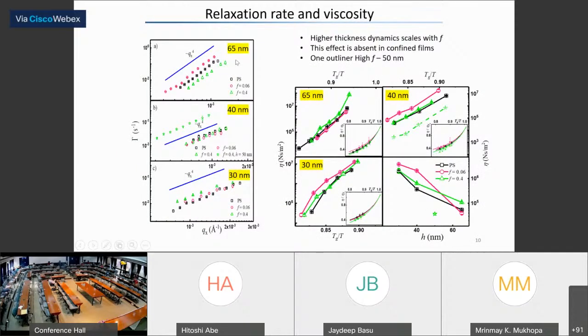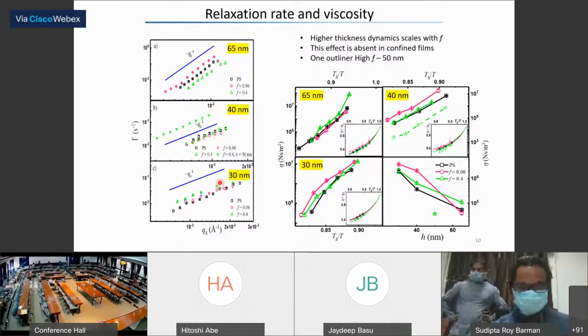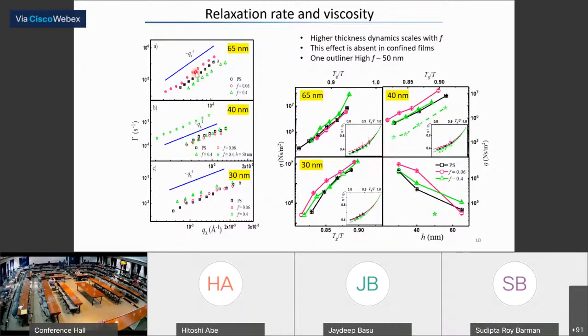So these are measurements for the different thickness of the films that we had, and this line is basically expected for capillary wave, and roughly the fit looks good. There is an expected variation in the rate with thickness: as the thickness decreases, the rate also decreases, which is what one would expect. So from this, basically to cut a long story short, what one can do is extract the viscosity.